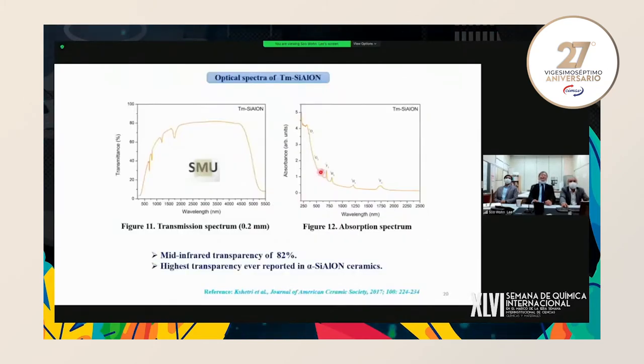So when you look at the transmittance of these materials from around 1,000 to 4,000, this is the infrared range. So there is 80% transmittance in the infrared range, but lower than infrared, the visual light transmittance is a little lower. But the absorption is always decreased. This is a very important issue. So we don't have much absorption of UV or visual light.